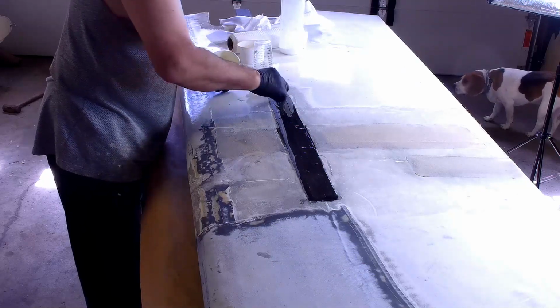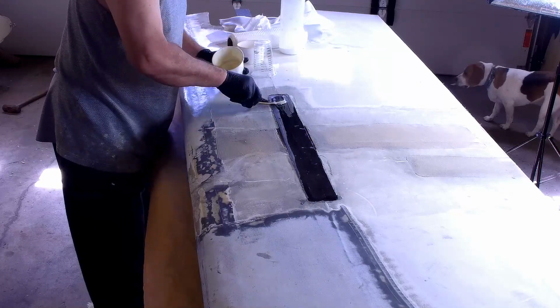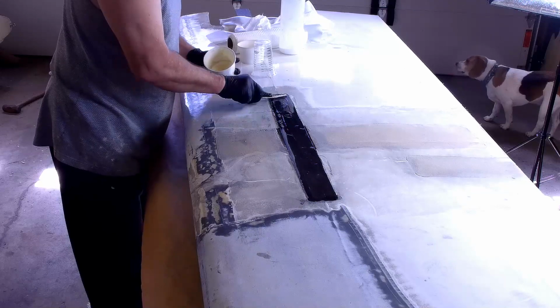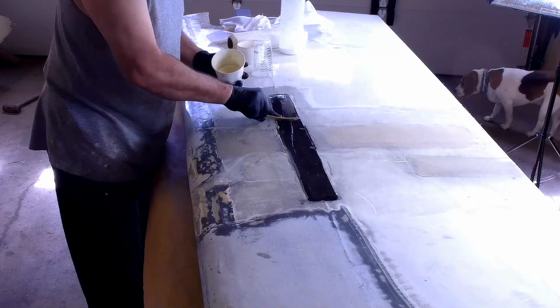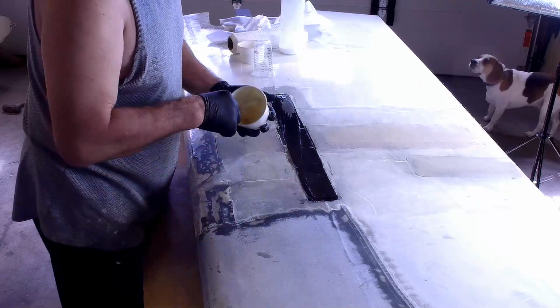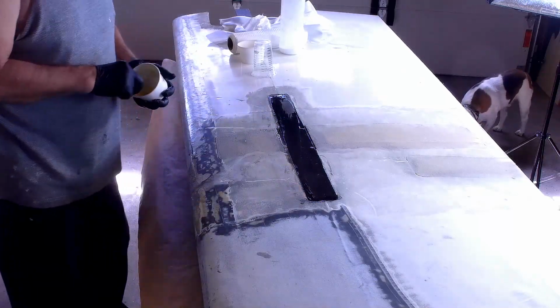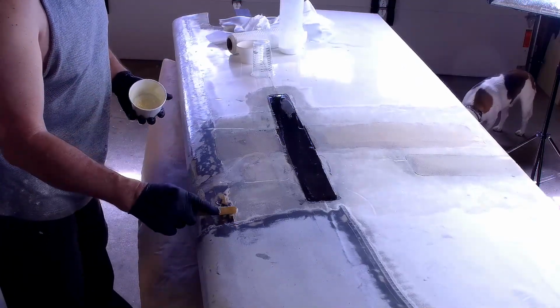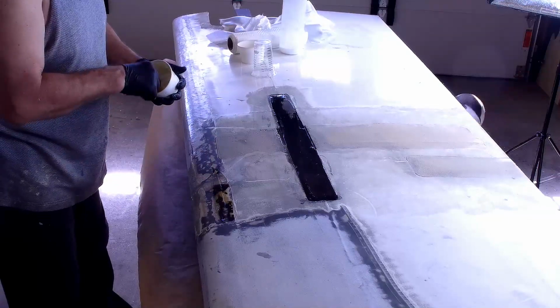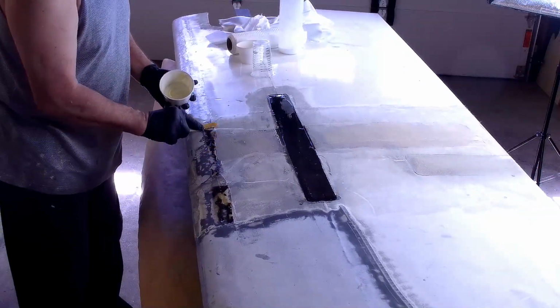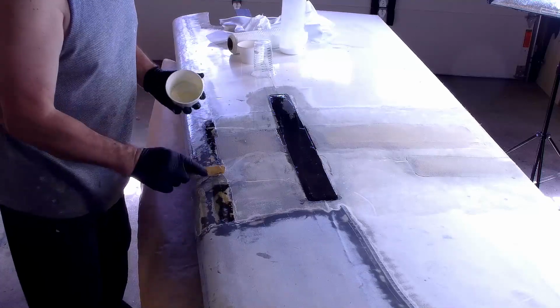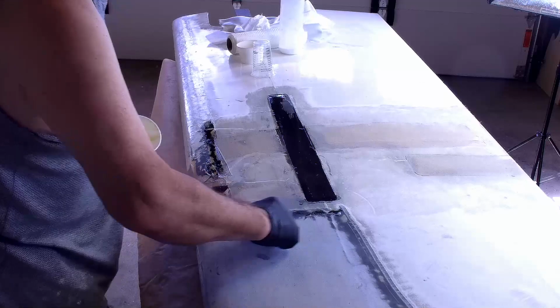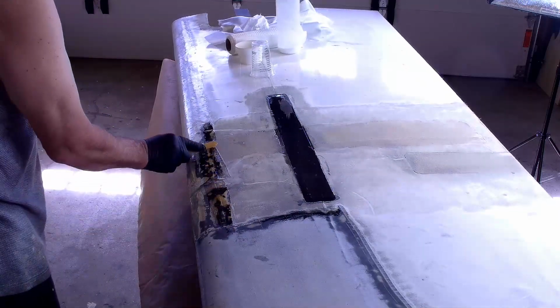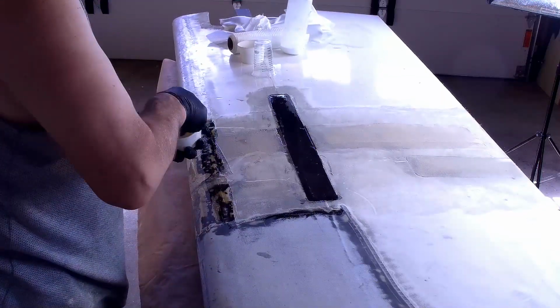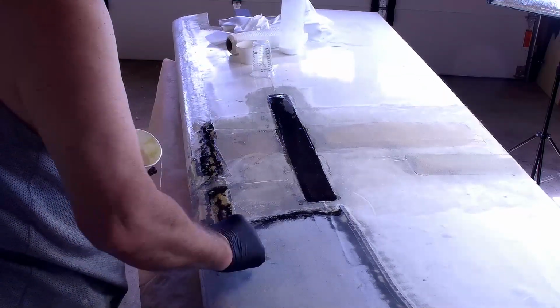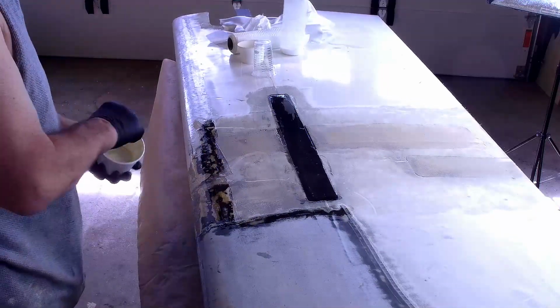This is nominally called a secondary bond or a post-cure bond, and I find it a much stronger assembly when you use a structural adhesive first and then apply the next layer of laminate using standard epoxy resin. If you use just regular resin on something that's been already cured, the bond shear strength isn't nearly as high. You do have to be careful. You have to check and make sure that your structural adhesive is compatible with your laminating resin. I'm using T88 here, and my laminating resin is the super hard epoxy resin from Tap Plastics, and I've used them for many years, and I've found them to be completely compatible.